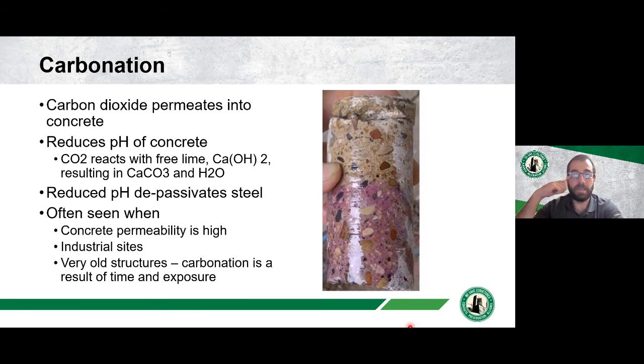We often see carbonation when concrete permeability is very high. If the concrete is very permeable, carbon dioxide will permeate into it very quickly. Industrial sites where you have a lot of emissions, carbon dioxide and monoxide, can cause carbonation quicker. And also very old structures. Carbonation is just a matter of time. As we move through time, carbonation keeps occurring on all structures. So historic structures tend to have this issue much earlier. Very old structures will eventually have this issue.